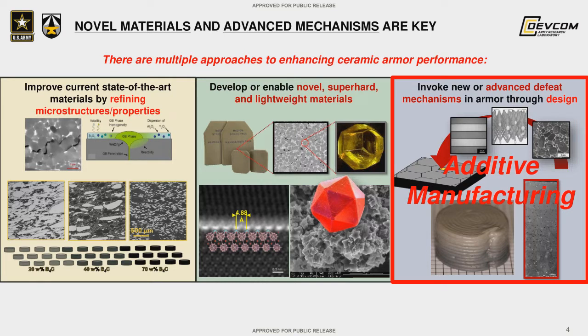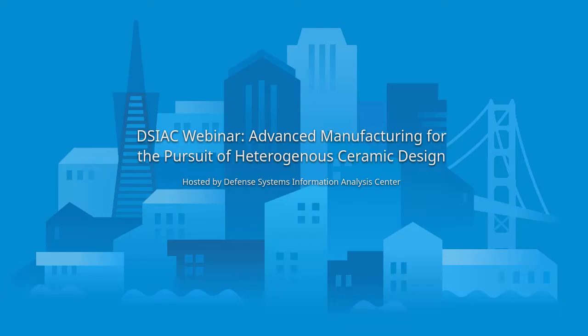So when we look towards the future and at improving the armor materials that we have, there's multiple approaches that we can take to enhancing ceramic armor performance, which is generally defined as the strength over the areal density. So how much performance you can get out of the least amount of mass per square inch of area. So one route is that you can try to improve the current state of the art materials, boron carbide or silicon carbide, by refining their microstructure and property.